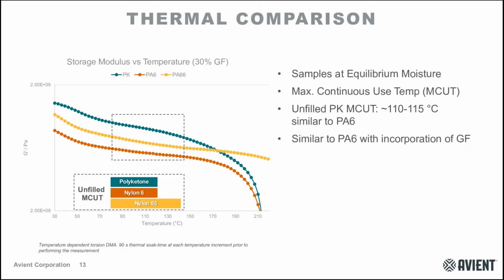In this case, we're measuring the elastic modulus change with increasing temperature. And I don't expect everybody on the webinar to be an expert in polymer rheology, but the important thing to note here is the shape of these curves and looking at the slope. And once the slope begins to change, what that tells us is that the material properties are changing to a noticeable degree and that we're in a region above the ideal use temperature of the material.